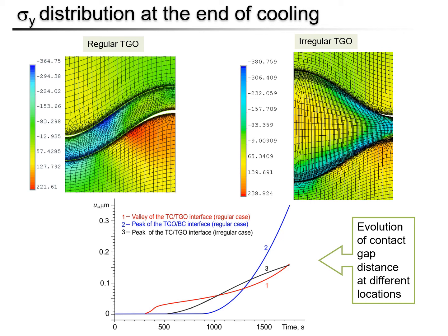Now let's move on to the case with the interfacial debonding. For the regular TGO, the debonding upon cooling occurs along both the TC-TGO and the BC-TGO interfaces. The location of crack nucleation corresponds well to the distribution of normal and tangential stress. First, the crack is initiated at the valley of the TC-TGO interface. Then the debonding progresses towards the peak location with the mixed mode mechanism. At the end of cooling, nearly all contact elements between TC and TGO layer are damaged.